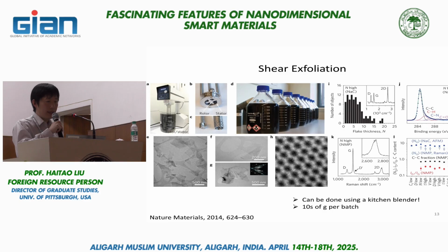And also, on the bottom, you see the Raman spectrum of the sample. I'm going to talk about Raman a bit more later, but the take-home message here is there's a very strong peak labeled as D. You may notice there's a D'. And what that D' indicates is there's a lot of defects in the graphene sample. Okay. So you can get decent graphene sample, but their quality is not that high.